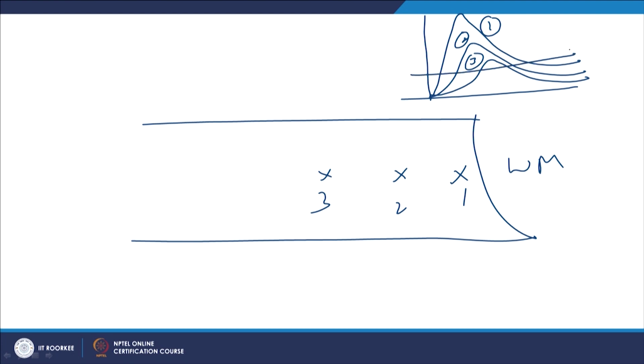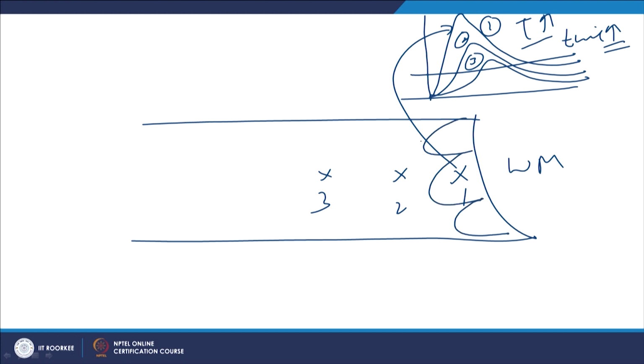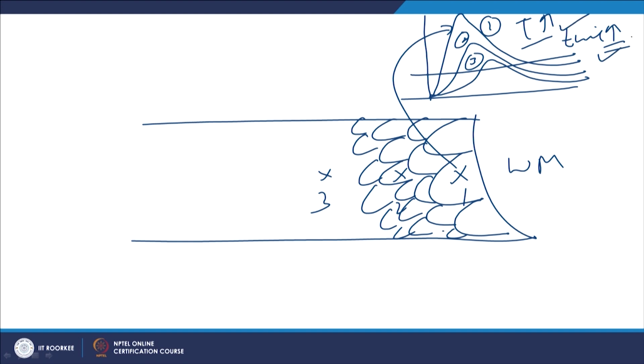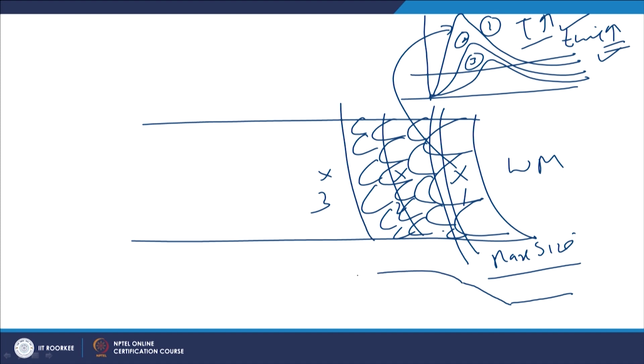So, if we take any particular temperature above which recrystallization is taking place and then grain growth is occurring, for location 1 the peak temperature will be high, as well as the high temperature retention, and both these factors will promote the maximum grain growth in location 1, while somewhat lesser grain growth will occur in location 2. So, the regions which are experiencing the maximum grain coarsening will experience the higher peak temperature for longer time, and the regions which have experienced the maximum size of grain will be the softest one. Where partial grain coarsening has taken place, the hardness will be somewhat high, and where grains are still fine, that zone will have the higher hardness.